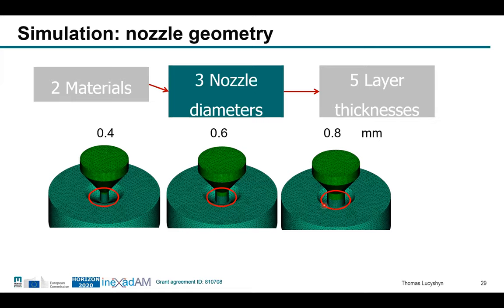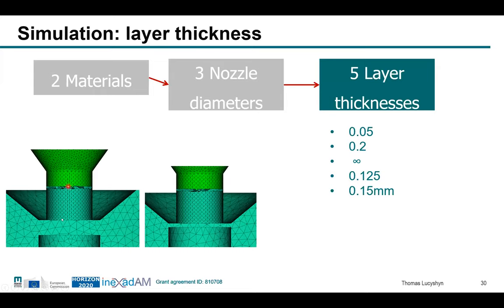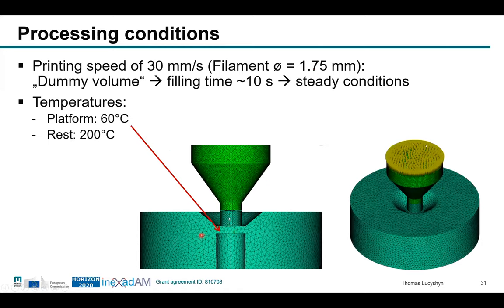And we also changed the layer thicknesses. So here the filament comes down and here's the die, and here the filament would come out, and we had a look at the distance here. In one situation, we had a very wide distance between the platform and the extruder die. And in the other extreme, we had a very small gap between the platform and the extruder die. So we varied these parameters, which is kind of mimicking the layer thickness of the deposited filament. And we did some parameter studies. And in the end, we wanted to see how the material behaves when it comes out here, and also regarding the powder concentration in this area. So the printing speed was set to 30 millimeters per second with a filament diameter of 1.75 millimeters.